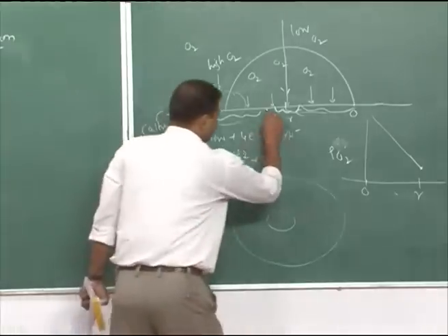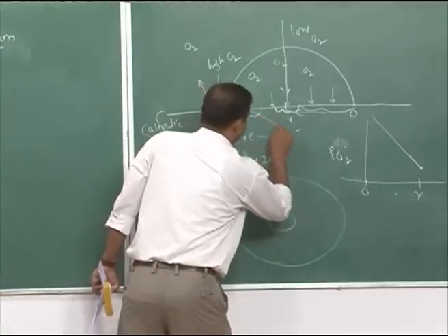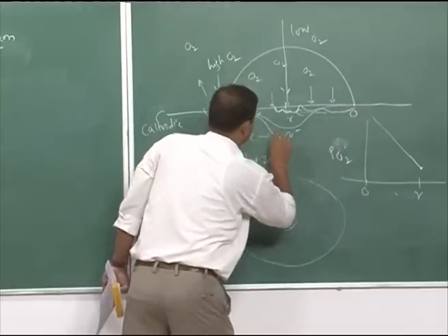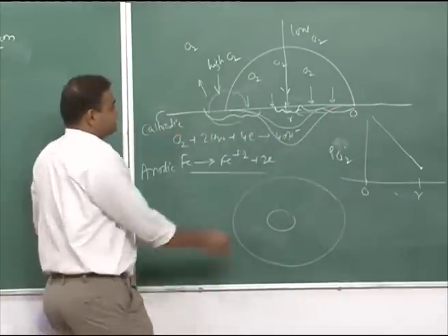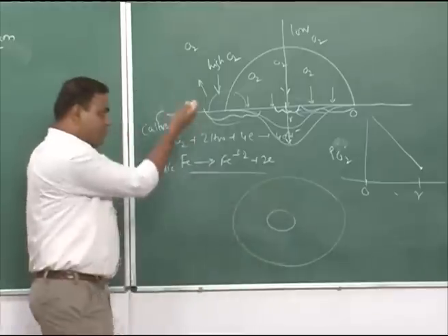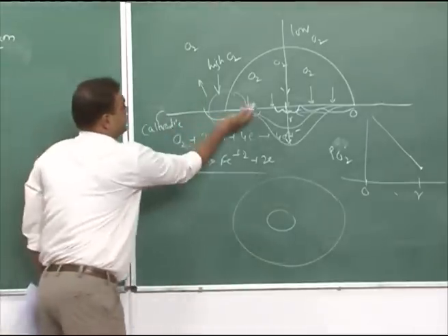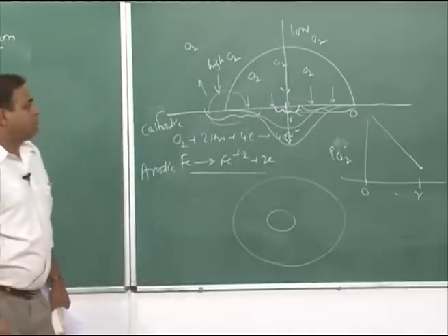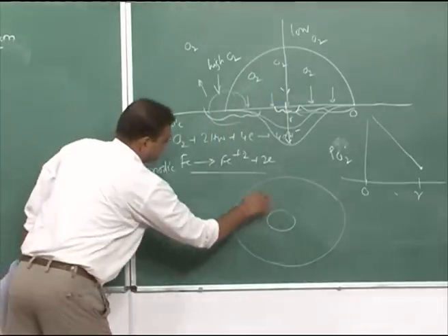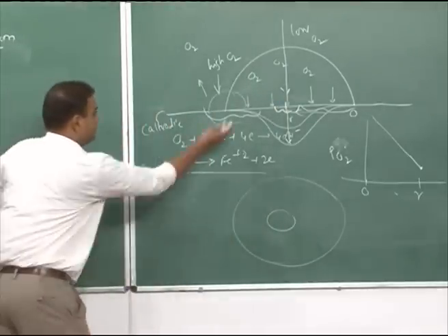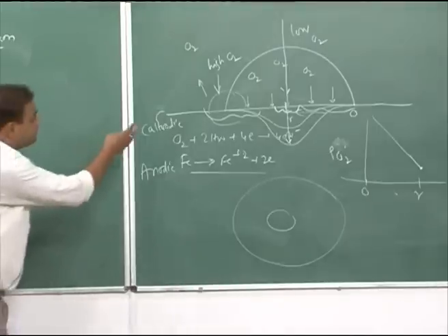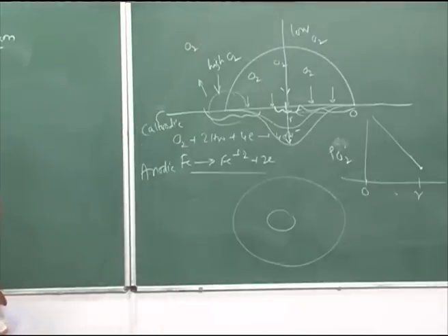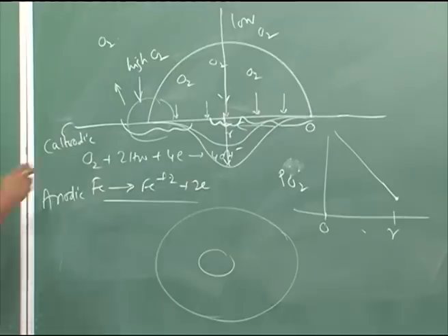Gradually we will see that the dissolution pattern would be like this. At the center part we have more and more dissolution compared to the periphery part of the water droplet or the rain droplet on a mild steel. This is a classic example of concentration cell development, and the consequence would be the corrosion at the center of the rain droplet.